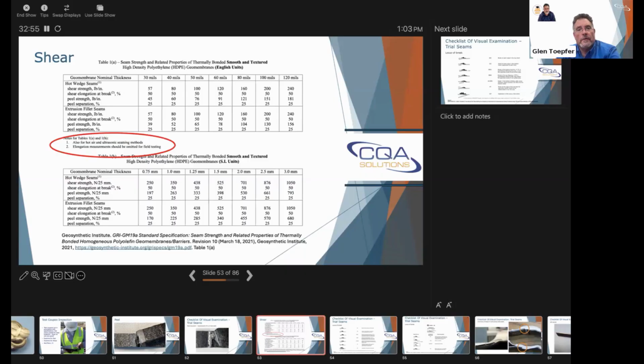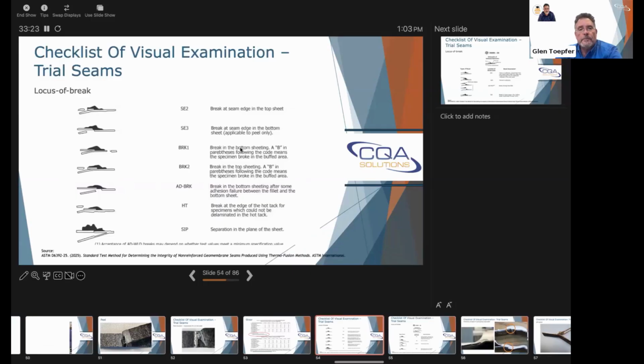And I think this is one of those, at least for extrusion coupons, because we get destructs back that fail. We get a few back every year that fail elongation. They're 25, 30% elongation, they fail. And now you've got to track destructs. Now you've got a bigger problem. You've got to fix things when potentially you could have avoided it in the first place with your trial welds, which is the whole purpose of the trial weld to begin with.